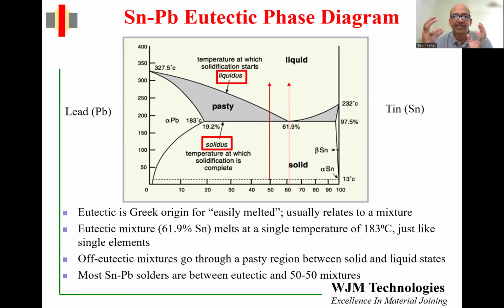So eutectic is an alloy which has the lowest melting point, but as soon as it melts, it becomes very liquid. For some applications, that's a good combination. But sometimes you want more of a pasty or more of a viscous fluid as the braze or solder. In this case, we're talking about soldering. So we can go to a 50-50 mix. You can buy a 50-50 mix of tin and lead, and that has an interesting behavior. When you increase the temperature from room temperature up to 183 and go slightly higher, you will find that only a small amount of that alloy starts melting. As you go higher in temperature through this range called the pasty range, you will find that an increasing amount of alloy becomes liquid. And once you go above the liquidus temperature, the entire alloy is fully liquid.